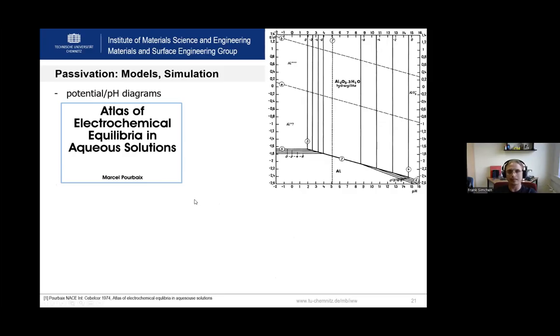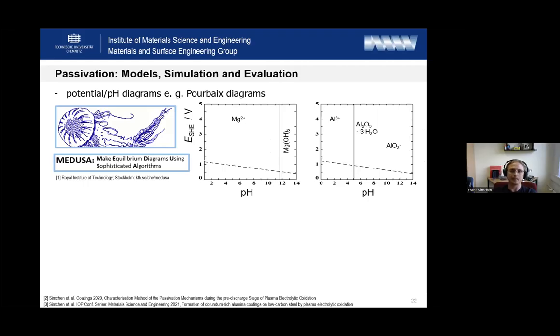And another scientist, Marcel Pourbaix, gave us one interesting tool to give an electrochemical prediction about the passivation behavior of certain electrolyte metal combinations, the so-called potential pH diagrams, which are also often called Pourbaix diagrams. And looking here, for example, for magnesium and aluminum, you have a statement about stability regions of your metallic substrate in dependency of the pH level and applied potential. So for magnesium, you would say in an alkaline range, the substrate could be stable because you form magnesium hydroxide, and in neutral to acidic range, you will get corrosion because magnesium ions just shift away. Aluminium, you have your stability range in a neutral region, and in acidic and alkaline environment, you also will not get any passivation.